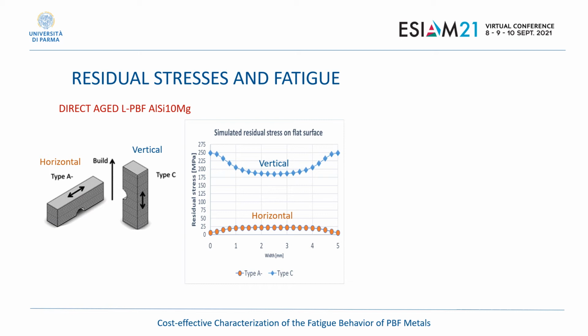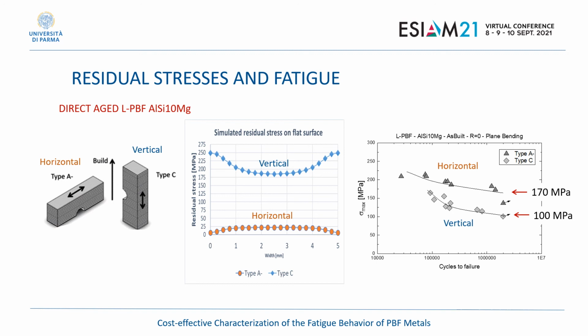We tested those specimens and we determined the data that are shown in this plot. Again, you can see that the horizontal specimens give a very good fatigue response. Those are the specimens without residual stress in them. On the other hand, the vertical specimens perform very differently and with much lower performance because of the presence of these high tensile residual stresses.